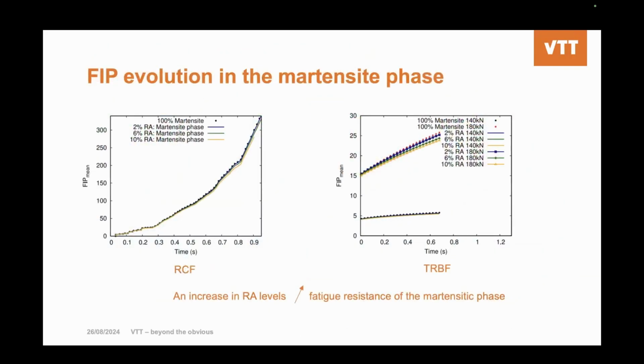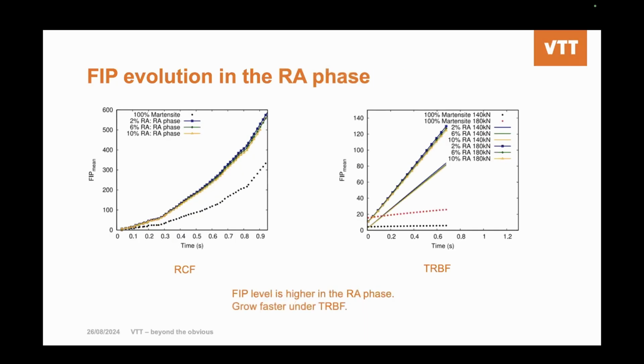If we analyze the average FIP in the martensite phase, you can see the black dot is 100% martensite phase, and the 10% is below it. That means an increase in retained austenite level could improve the fatigue resistance of the martensite phase. A similar trend we observed in the root bending fatigue tests. But here we see two groups of curves. They are from different pulsating force levels. If we analyze the FIP evolution in the retained austenite phase, not in the martensite phase, we see that the FIP level is higher in the retained austenite phase, but grows faster in the tooth root bending fatigue, from the right side image. So let me conclude.